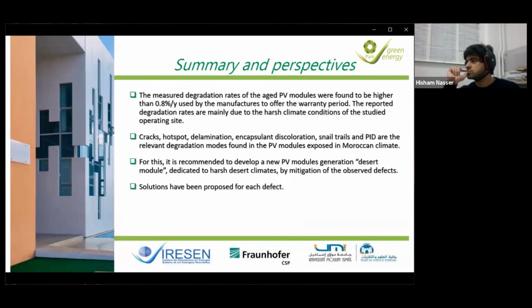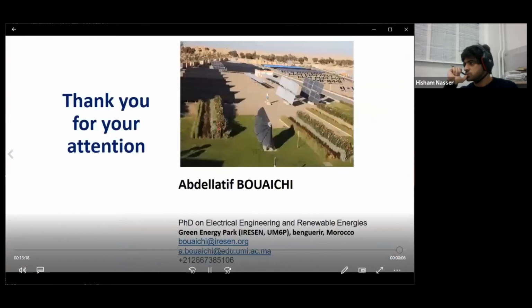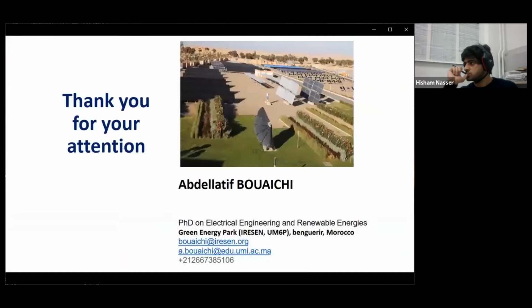The observed degradation modes are cracks, hotspots, delamination, encapsulant discoloration, snail trails, and PID. For this, we recommend developing a new PV module by mitigating these real degradation modes in the climate of Morocco, and some solutions have been proposed. The next step is the validation of the proposed solutions by accelerated aging tests and by outdoor conditions in Morocco. Thank you for your attention.